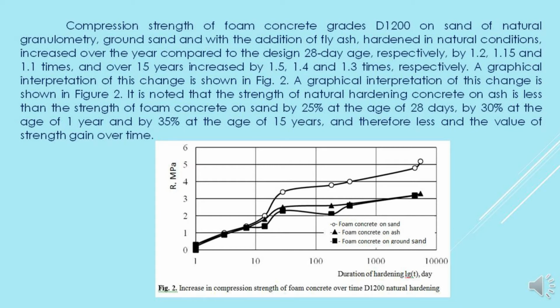The graphical interpretation of this change is shown in Fig. 2. It is noted that the strength of natural hardening concrete on ash is less than the strength of foam concrete on sand by 25% at the age of 28 days, by 30% at the age of 1 year, and by 35% at 15 years, and therefore lessen the value of strength gain over time.